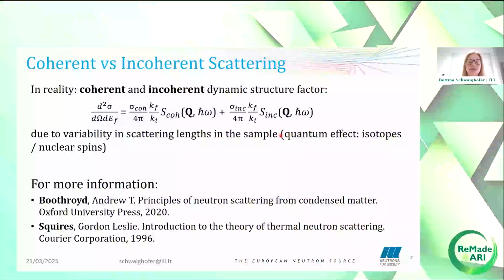The coherent scattering depends on the mean scattering lengths, whereas the incoherent scattering depends on the variance of the scattering lengths. So if we have a random variability of scattering lengths in the sample, for example, through isotopes or nuclear spins that are not zero, then the incoherent contribution arises. This is quite a complicated part of neutron scattering to explain briefly, and therefore, if you're interested, I can highly recommend these two textbooks for a nice derivation of the equation.